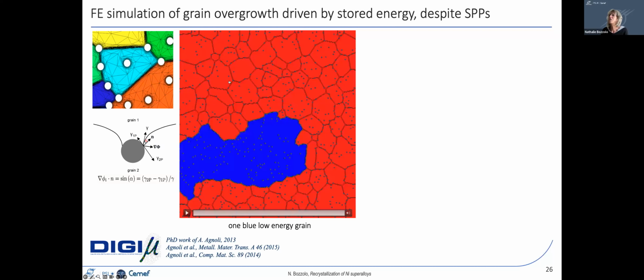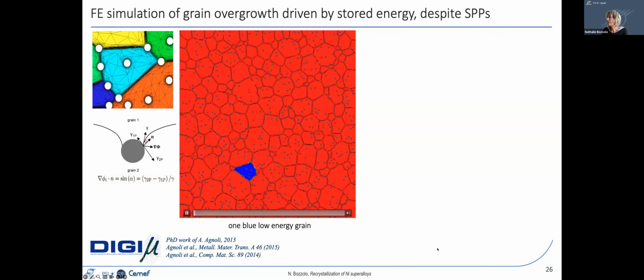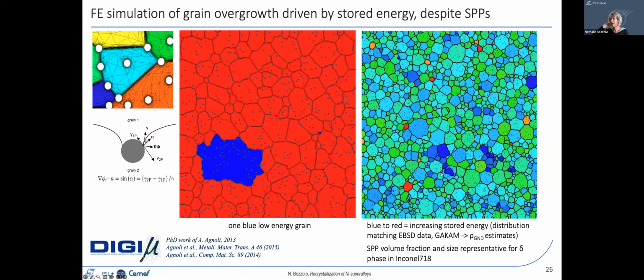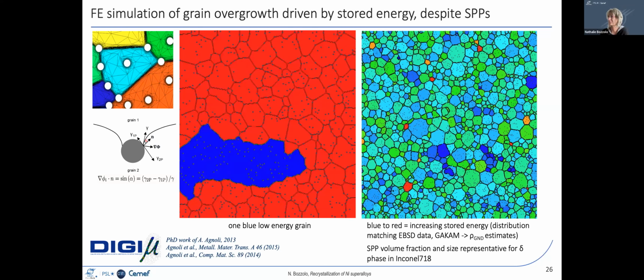We have also calibrated another simulation based on EBSD data. With EBSD data, we can approach the stored energy distribution through the orientation gradients we can measure in the grains. And so in an EBSD map, you can average the local misorientations you measure inside each grain and describe the average stored energy level present in the grains of the microstructure.